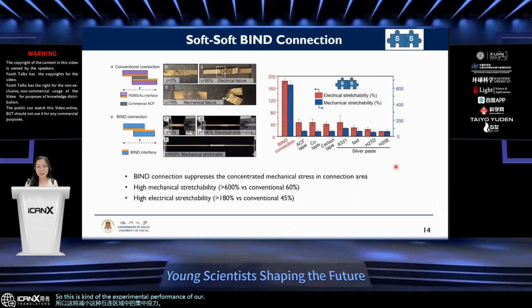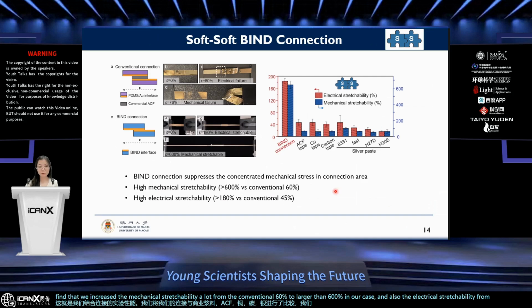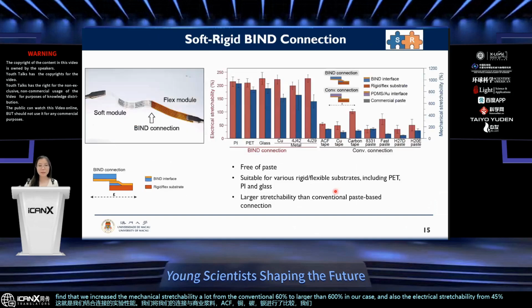So this is the experimental performance of our bind connection, and we compared our connection to the commercial paste, ACF, copper, carbon, and silver. We find that we increased the mechanical stretchability a lot, from the conventional 60% to larger than 600% in our case, and also the electrical stretchability from 45% to larger than 180%.